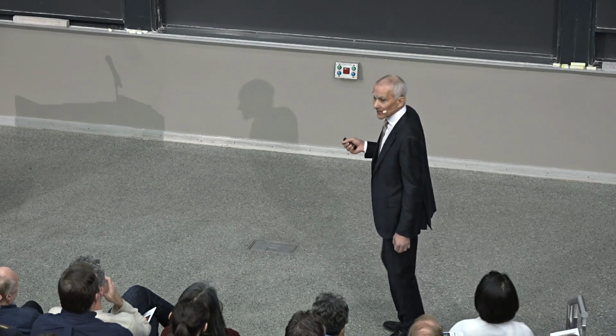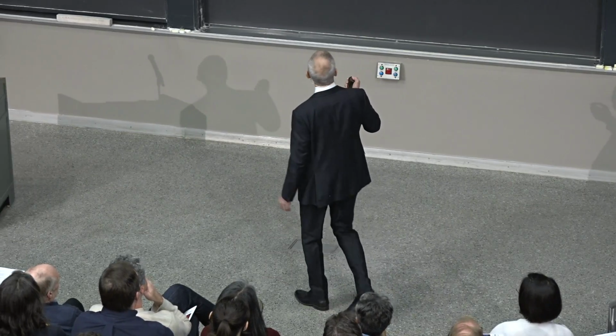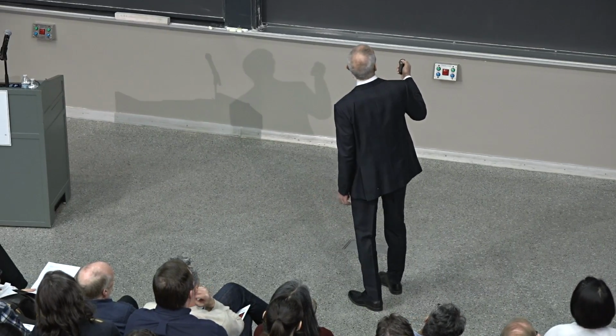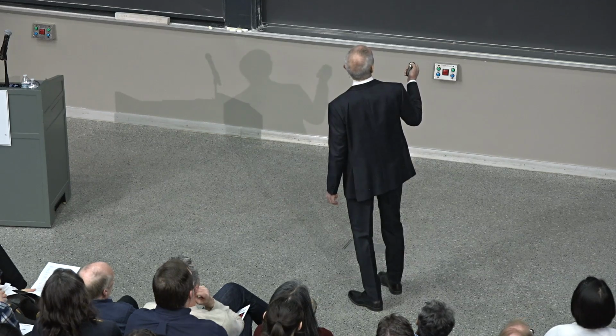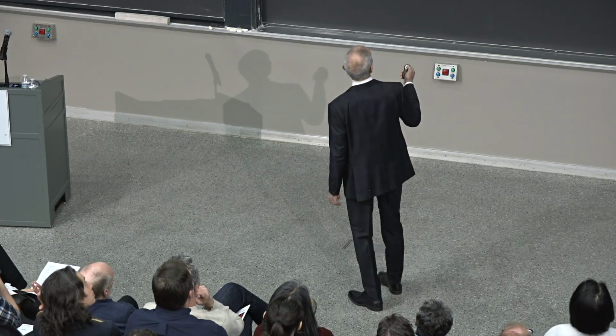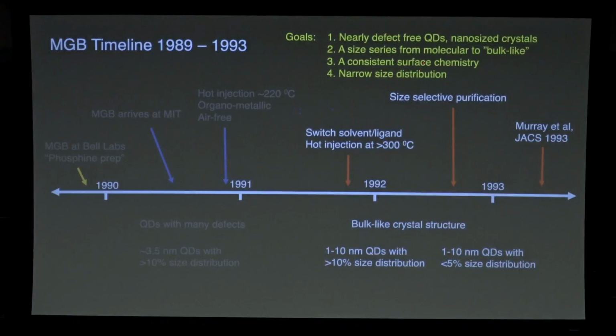So we had to switch things around. We wanted to have a higher temperature. You know, my goal coming to MIT was nearly defect-free quantum dots, a size series, consistent surface chemistry, narrow. So we had the consistent surface chemistry and the narrow size distribution after this, but we didn't really have a size series in order to study the physics from atomic to bulk. You want a size series.